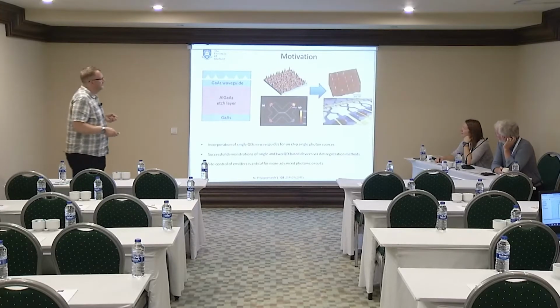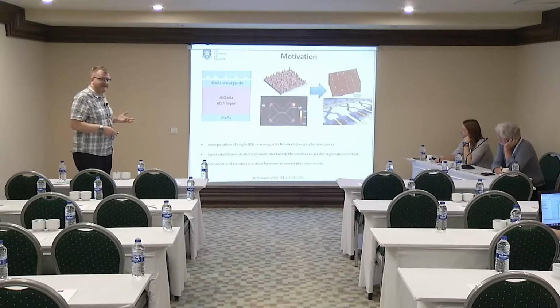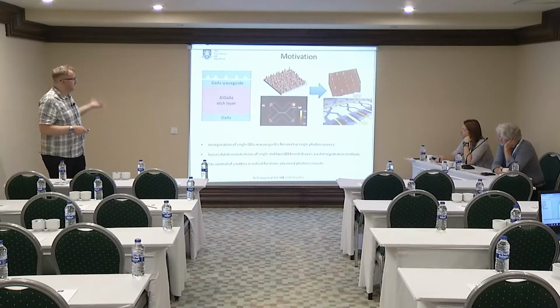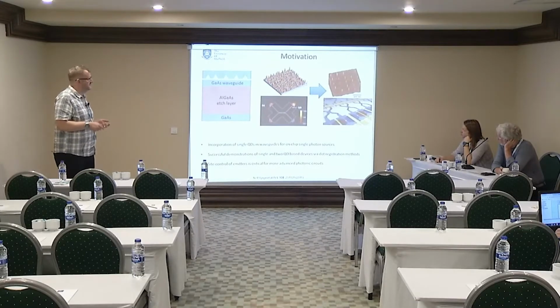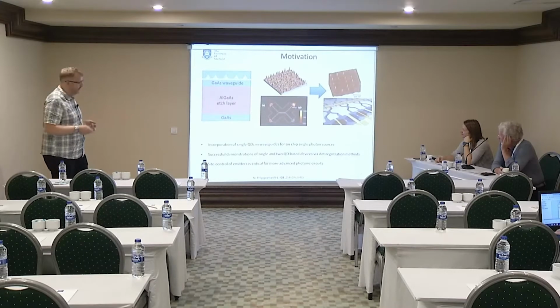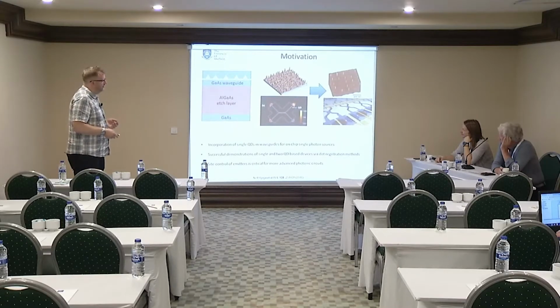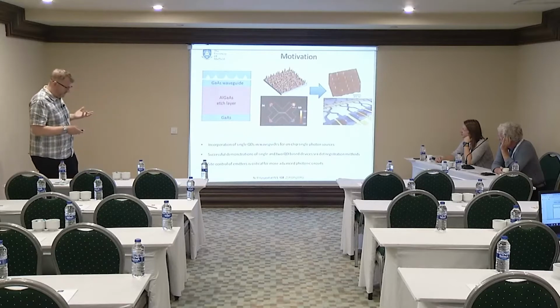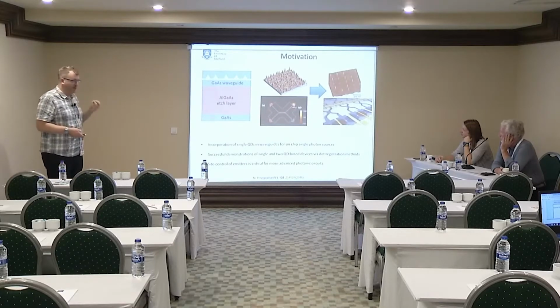If we want to move towards arrays of devices, then we can't have this random positioning of the dots. We have to start putting the dots in known positions so that we can fabricate structures next to each other. We can plan where the waveguides are going to go. In this case, what we'd actually have in the end, in the idealized picture, is tunable structures. So we have N and P-type doping, put electric fields across the dot to tune the wavelength. And then you would also have tunable beam splitters in order to optimize the circuit. So if we want to make something much more complicated, we need to know where the dots are.